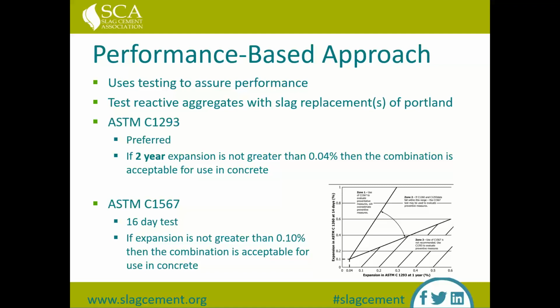In this case, slag cement. So you'll test your aggregate with a particular slag, usually with different replacement levels for both of these tests, and find a replacement level that properly mitigates ASR. Again, the 1293 test, this time we're going to 2 years, not even just 1 year, but looking for a 2-year result. And similar to C1260, the 1567 is a 16-day test.